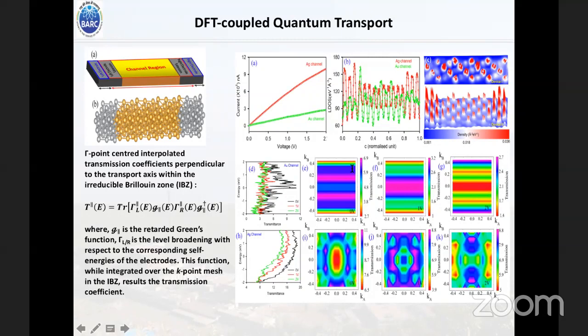And whenever we take the transmission color map, you can see that for the system, these transmission color maps are calculated perpendicular to the transport axis. So there are pockets which are very much inhomogeneous. For the Ag channel system, these are very much inhomogeneous, and there are highly transmitting pockets here. So even for the best possible devices, in the simplest possible devices within this system, there are large amounts of inhomogeneities present within the system.